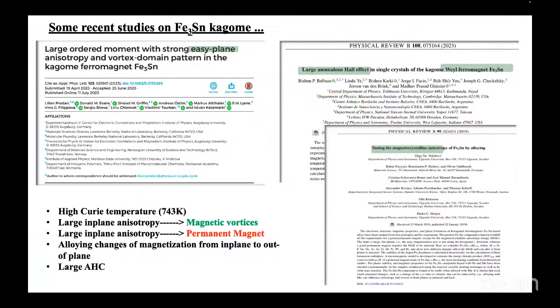So these are the recent studies done on the 3D Fe3Sn, the experimental and theoretical investigation that further points out the important features witnessed through experiments: a high Curie temperature of about 743 Kelvin, a large in-plane anisotropy, and experimentally they have also observed some kind of formation of magnetic vortices.